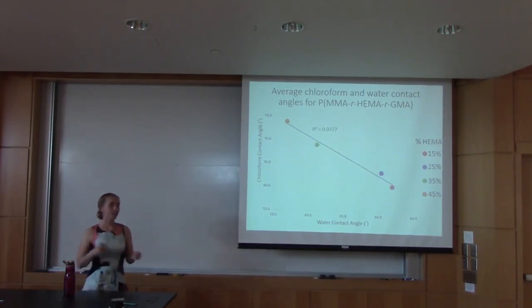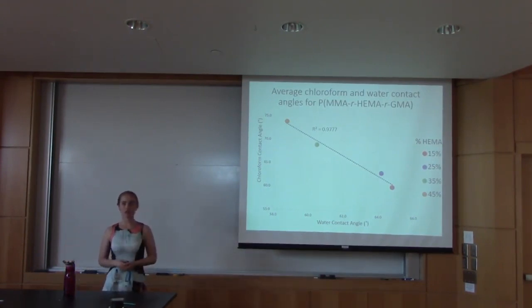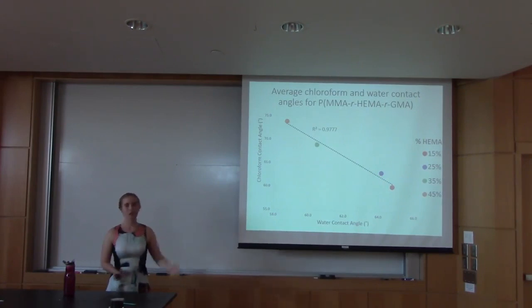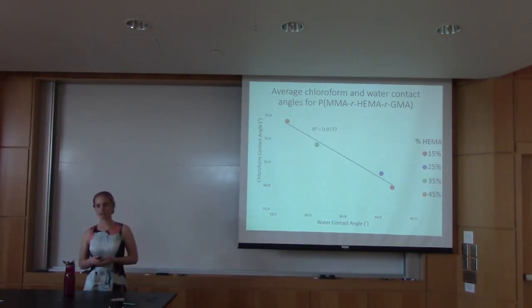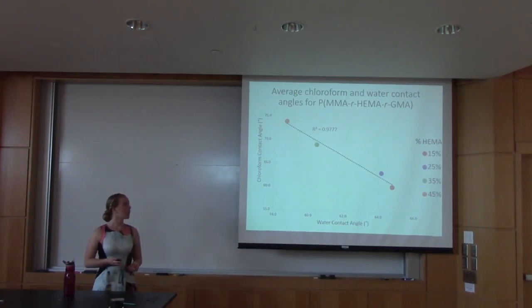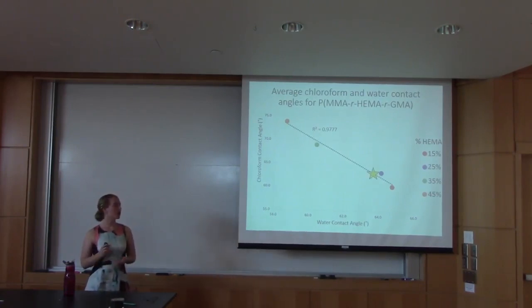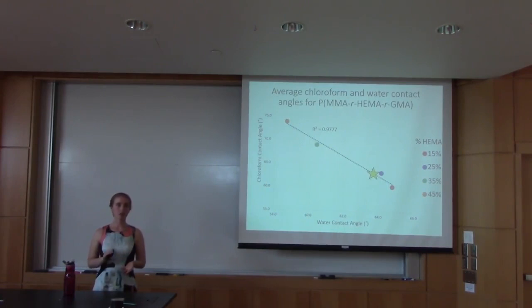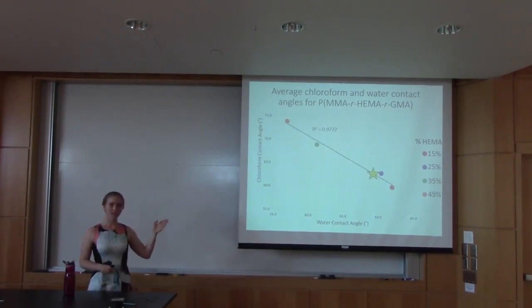And what's important to note is that for a truly non-preferential surface, we would need our water contact angle to equal our chloroform contact angle. So 60 degrees water contact angle and 60 degrees chloroform contact angle, for example. So with this particular polymer, or this random copolymer, that would be about 63, 64 degrees. So you can see our purple 25% HEMA right there is pretty close to that.